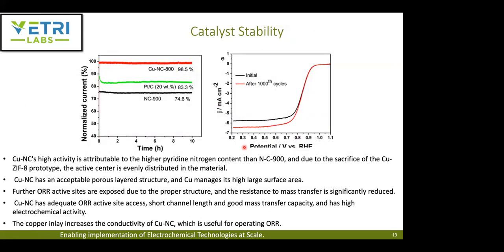And they tested the catalyst stability with chronoamperometry. They did it for about 10 hours. And what they found was their best performing copper nitrogen doped carbon catalyst had a loss of only about 1.5%, maintaining about 98.5% of the initial current. Whereas the platinum carbon lost about 16.7% and maintained only about 83.3%, and the nitrogen doped carbon lost about 25.4% and maintained only about 74.6%. So this tells you overall, after cycling for about 10 hours, you can still have a very low loss and maintain good stability for your copper nitrogen doped carbon at 800 degrees Celsius.